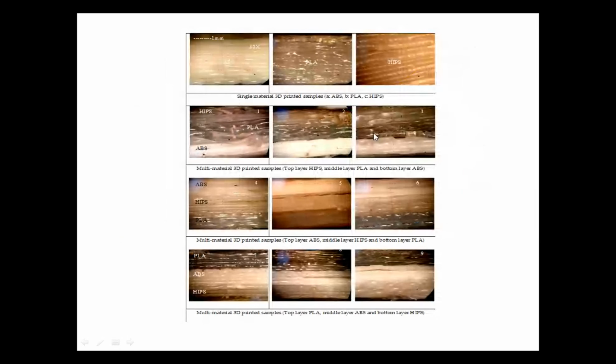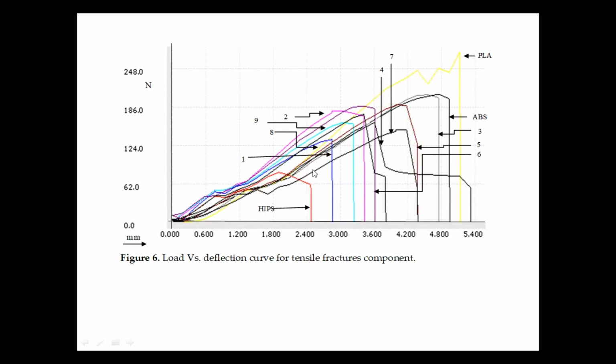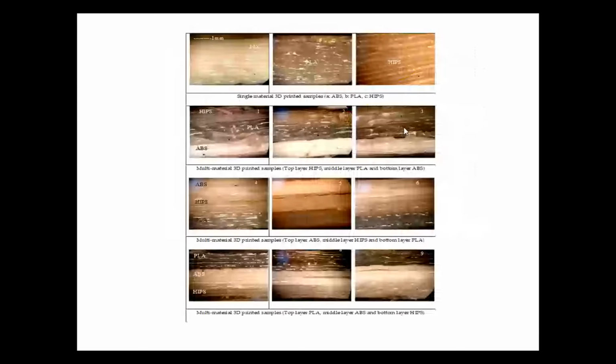So we can actually correlate while printing, and even for the managing of the waste, which layer I should print in the bottom, which layer in the middle, and which layer at the top, so that there could be better mechanical properties. And I can correlate this with the thermal stability also, right? Here you can see in curve number 7, I am getting a very fine layer followed by HIPS, followed by ABS, followed by PLA. If you just see curve number 7, this is giving me a very good result, right? Of course, these are comparable with the virgin material also, right?